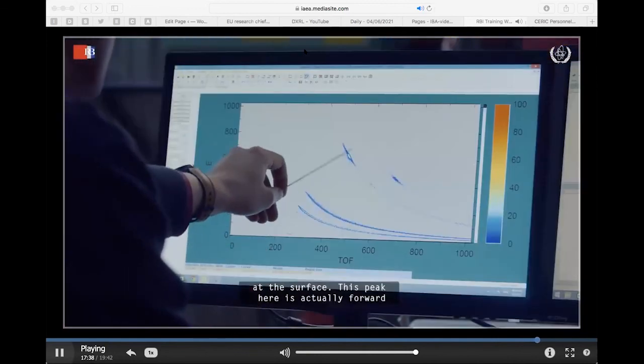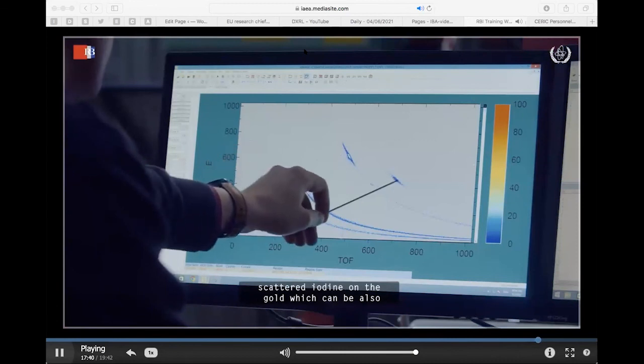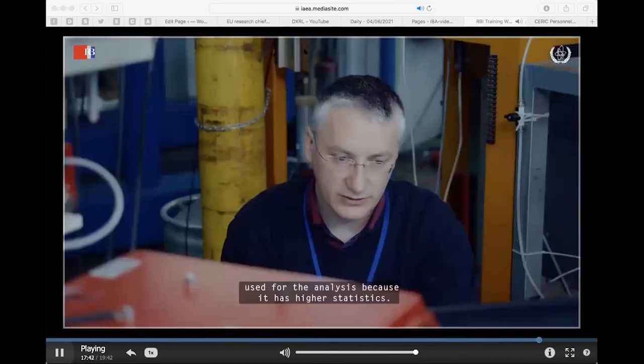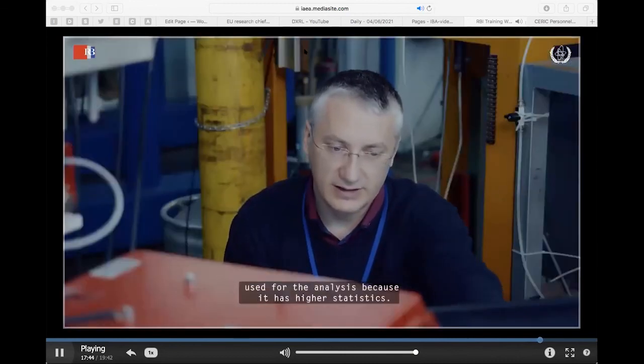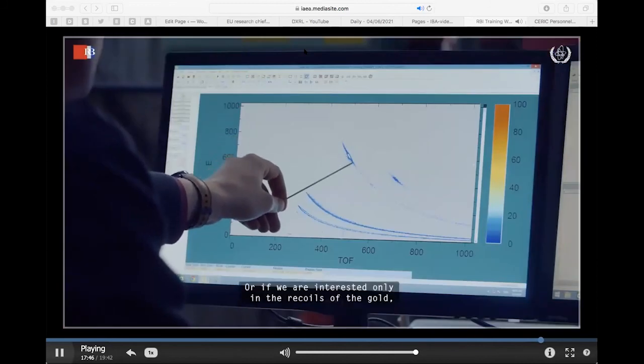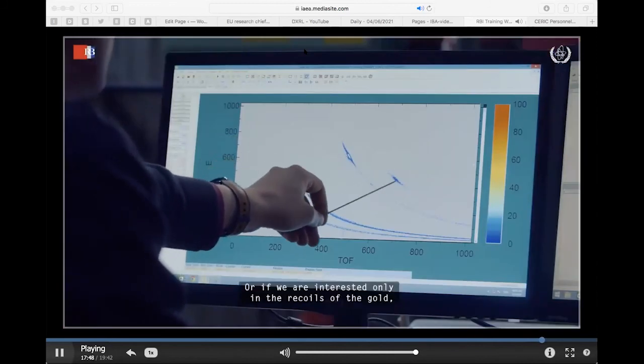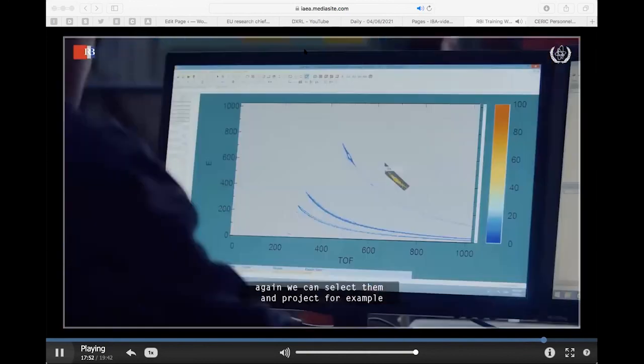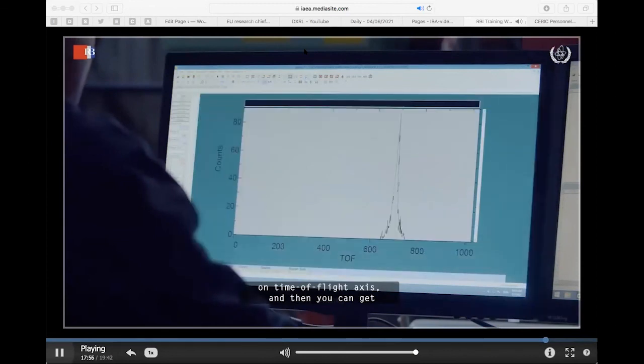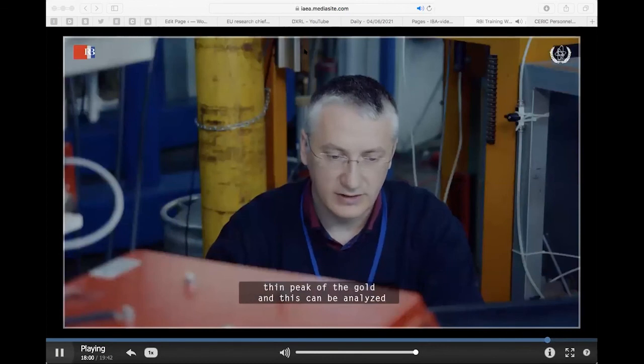This peak here is actually forward scattered iodine on the gold, which can also be used for the analysis because it has higher statistics. Or if we are interested only in the recoils of the gold, again, we can select them and project on, for example, the time axis, and then you can get the thin peak of the gold, and this can be analyzed using standard software packages.